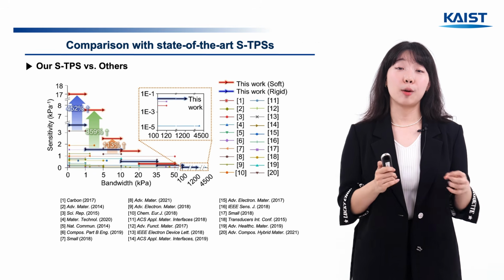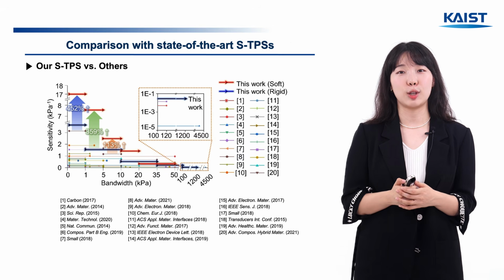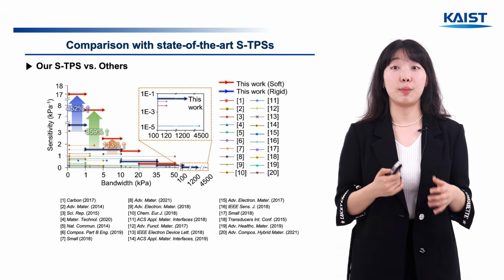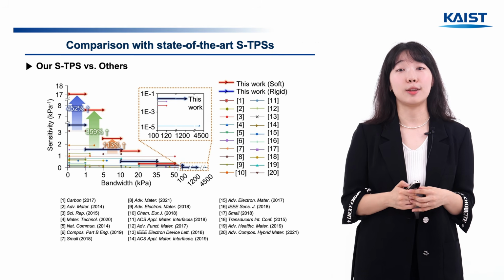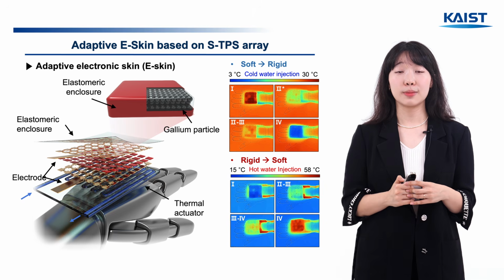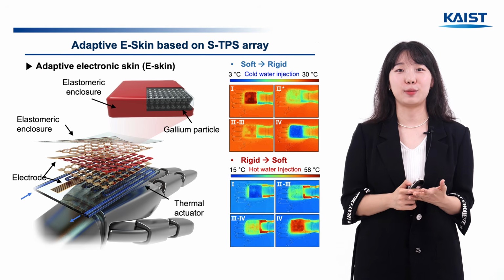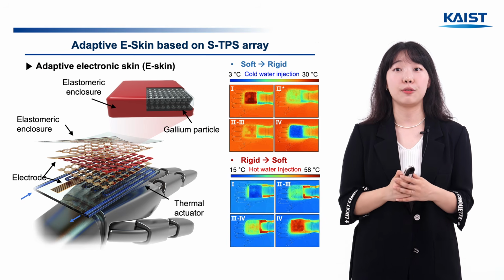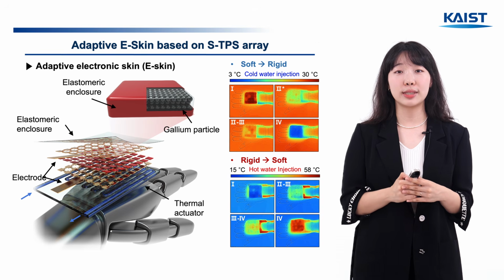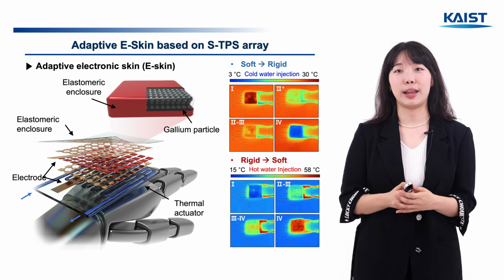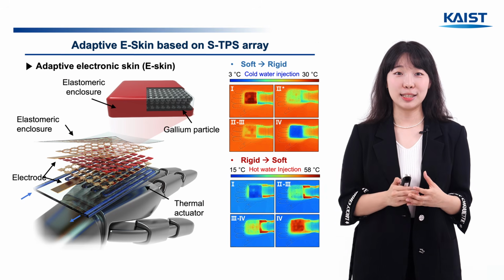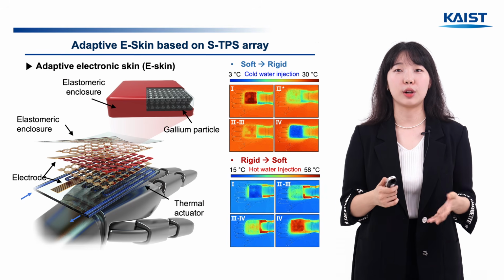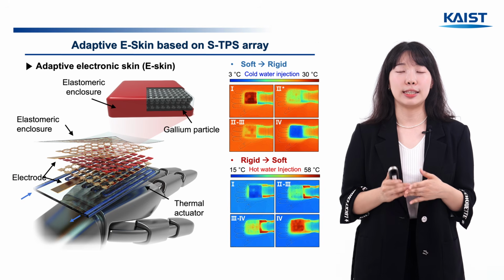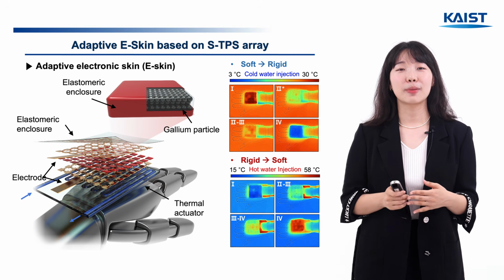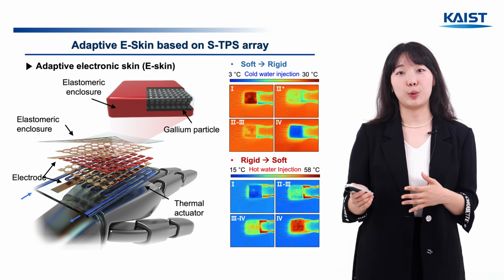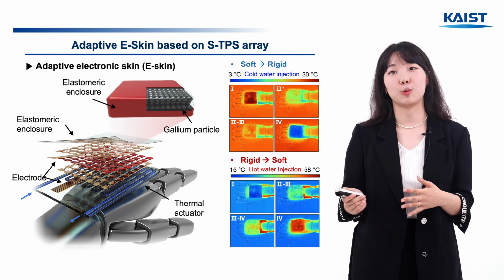So comparing the performance to other stiffness-tunable pressure sensors, the sensor that we made showed both high sensitivity and a wide measurement range. And because the T-shaped microfluidic channel produces particles of uniform size, we could build uniform sensors and scale them up into an array. We then integrated this with a microfluidic temperature controller underneath to create a stiffness-tunable electronic skin. The temperature controller switches between modes by running cold water and hot water through it.